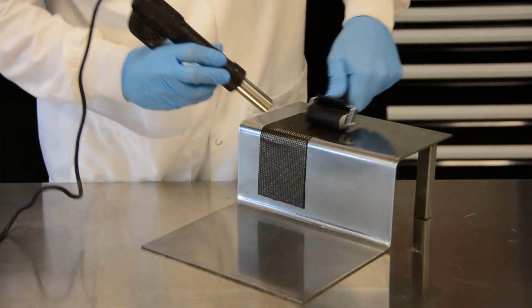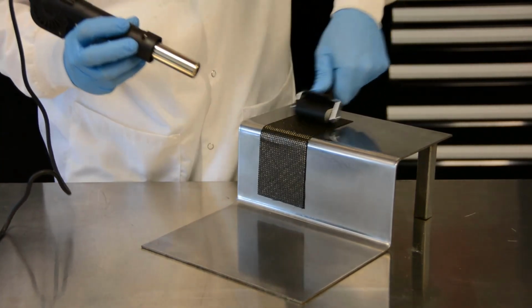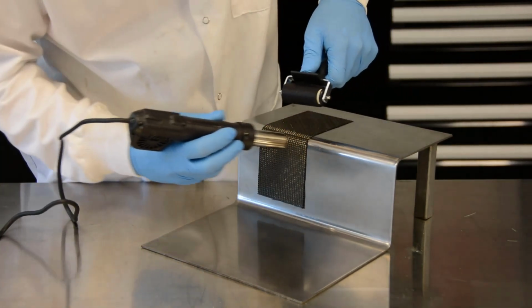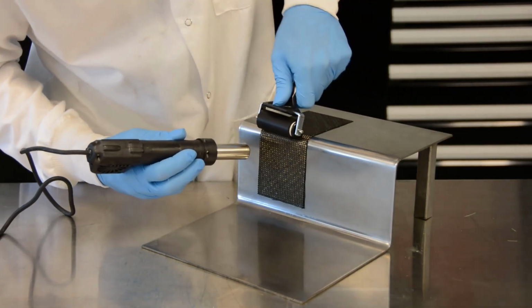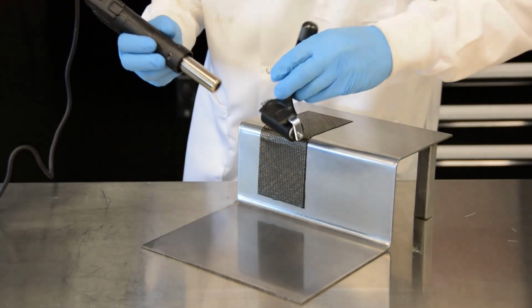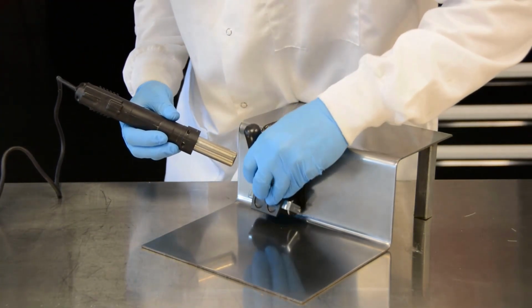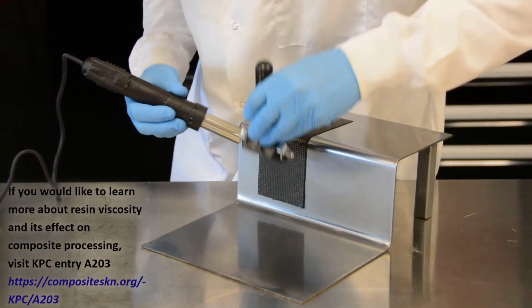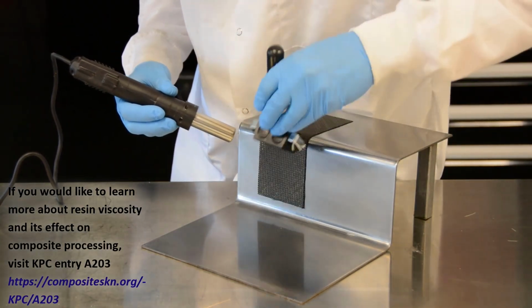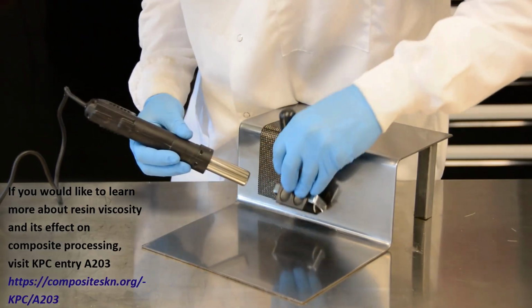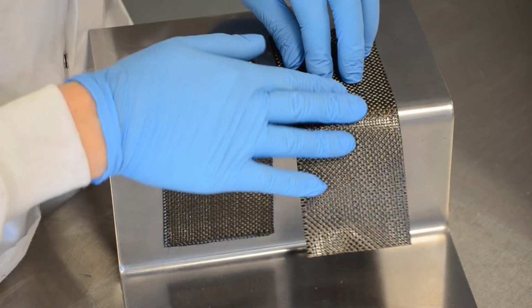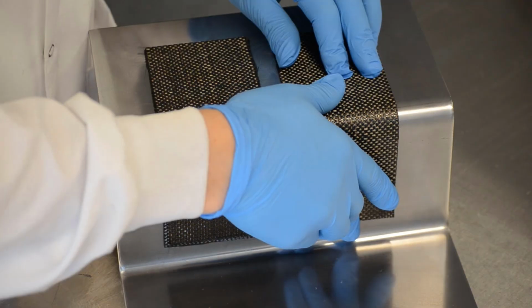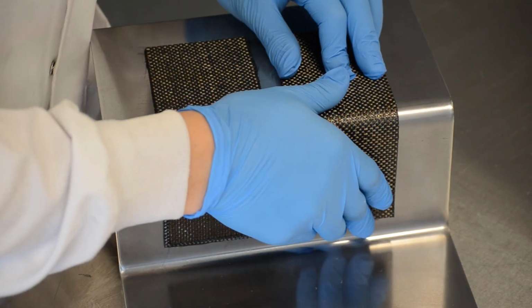Male L shape. Now, we will observe some other defects common to different geometries of prepreg parts. First, we will produce two parts on the outside corner of the tool. The first will be debulked partway through and the layers will be carefully positioned. A heat gun will be used to improve pliability and tack by reducing resin viscosity, and a roller will be used to ensure layers are fully pressed into place. The second part will not be debulked and the layers will be placed without using a heat gun.